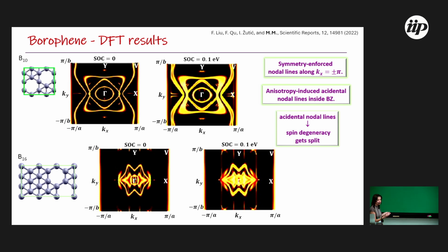We just did it as a test, since it is above the present capability of inducing spin-orbit coupling with an electric field in such materials, because these atoms are so light. But it shows that although accidental, these nodal lines are still very robust: even if you could crank spin-orbit coupling all the way up to 0.1 electron volts, the nodal lines would still be there.